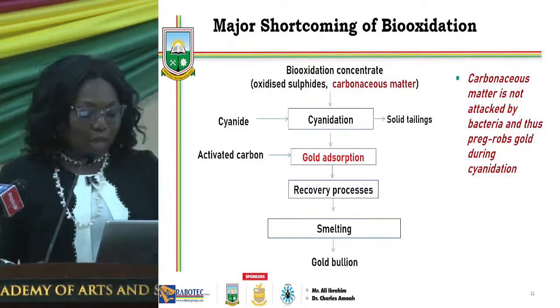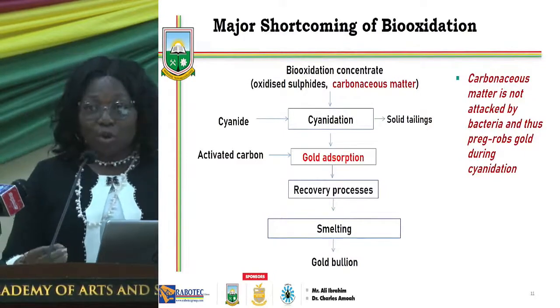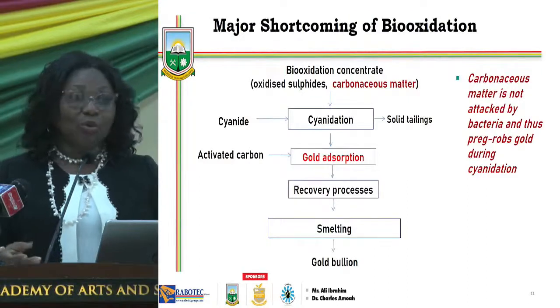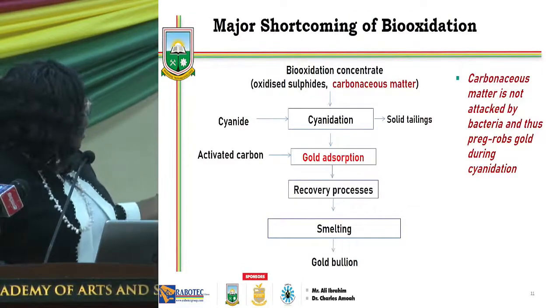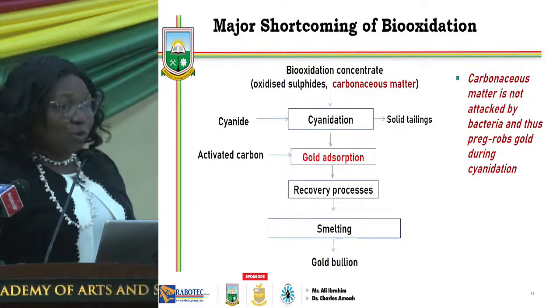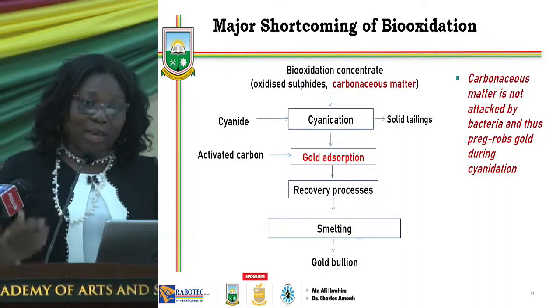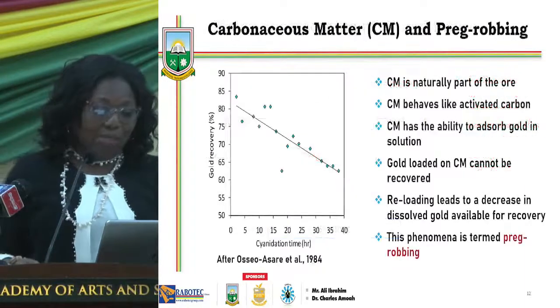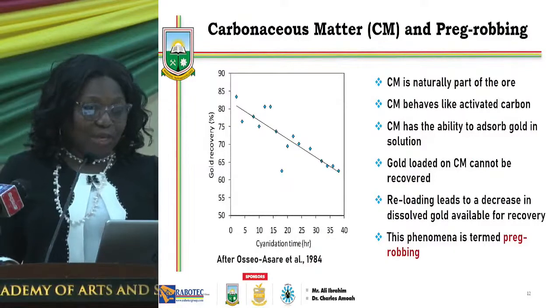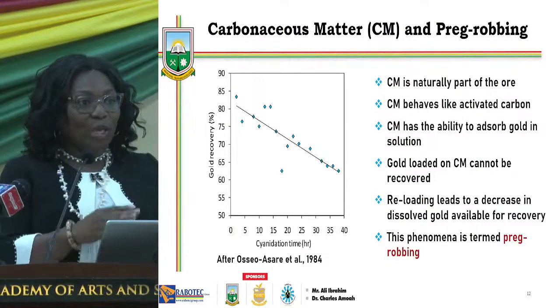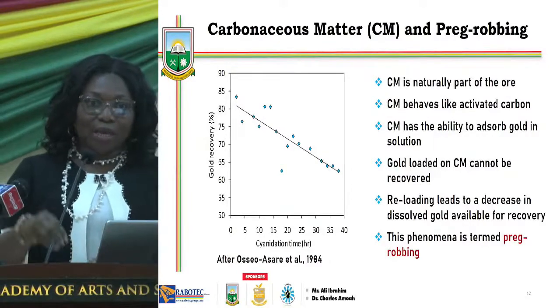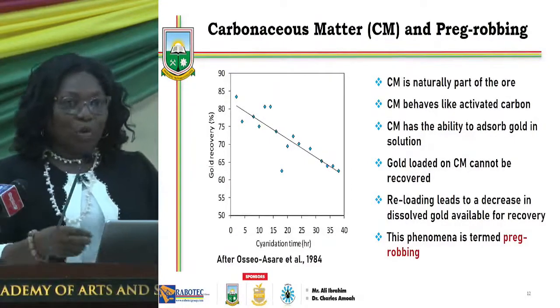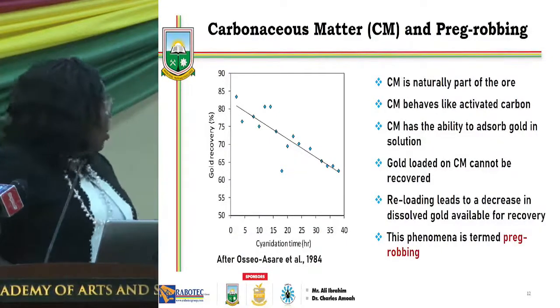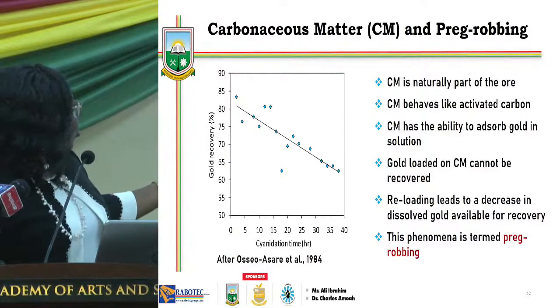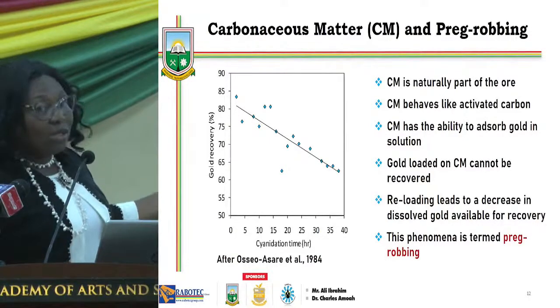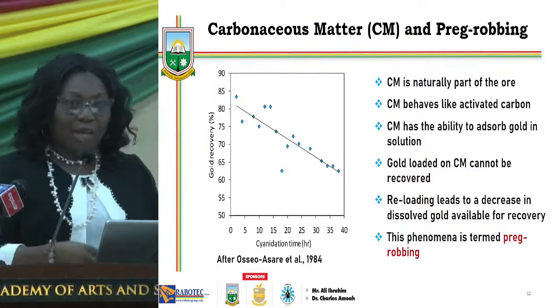So this diagram here is showing us the serious effect of carbonaceous matter in gold ores. From the reference, you see 1984. So this problem has been with us, and researchers have tried to solve it ever since. What this diagram is showing is that we have gold in solution, and as we allow it time, the carbonaceous matter in the solid is picking the gold back into the solid. And so the gold that should be available for us to recover is not available because carbonaceous matter is taking it out.